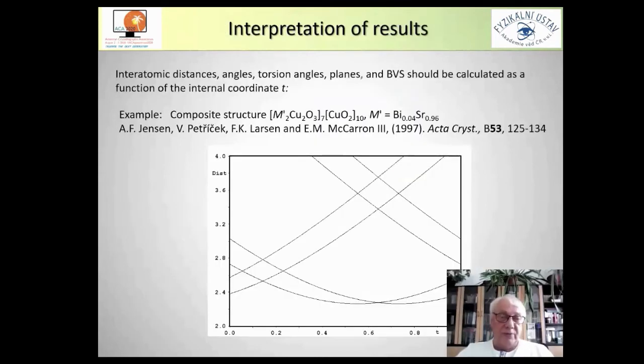Similarly, as for regular structures, we are also calculating interatomic distances, angles, torsion angles, planes, and bond valence sums as a function of the internal coordinate t, which means how they change from cell to cell because of modulation. For composite structures, it's very specific. If we take only the composite principle, which means different periodicity in these two subsystems, we can get functions like this. You can see here for distances between oxygen and strontium atoms, we have very different minimum distances, and here, for example, we have 2 different distances and very long ones. Here we have 2 a little bit longer than here, but it makes in fact no real sense.